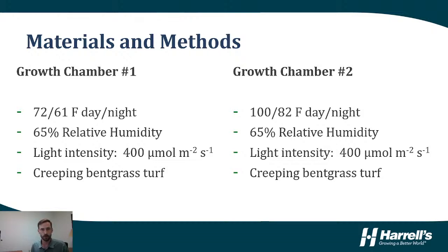So we had two different growth chambers that we used for the trial. Growth chamber number 1 had a day-night temperature of 72 degrees and 61 degrees Fahrenheit, 65% relative humidity, and creeping bentgrass turf, so very ideal growing conditions for bentgrass turf. Growth chamber number 2, on the other hand, was a bit more of a death chamber. 100 degree Fahrenheit day temperatures, 82 degree Fahrenheit night temperatures, again 65% relative humidity. In addition to the heat stress, Dr. Zhang also induced some mild drought stress into growth chamber number 2 as well.